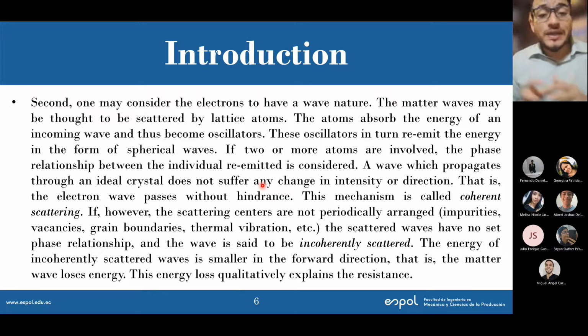But if the scattering centers are not periodically arranged, so that means if I have impurities, lattice imperfections, right? Vacancies, impurities, grain boundaries, dislocations, thermal vibration, everything. If I have that, the waves will be scattered, and then I have to see the phase relationship. And then obviously the wave will be incoherently scattered. There is no phase relation between one wave and the other, between one wave coming from one atom and another. Then the wave is incoherently scattered. And then I have resistance.